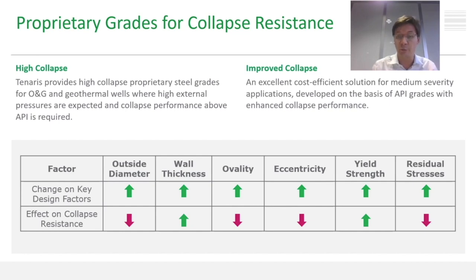Tenaris has developed a portfolio of solutions, looking for the most cost-effective ones, in order to optimize the performance of our pipes in terms of collapse resistance. We developed a series called High Collapse, where we maximize our collapse resistance depending on the specific size and grade, and also another series called Improved Collapse, which is a more cost-efficient solution, still providing a significant improvement with respect to API standard collapse resistance.